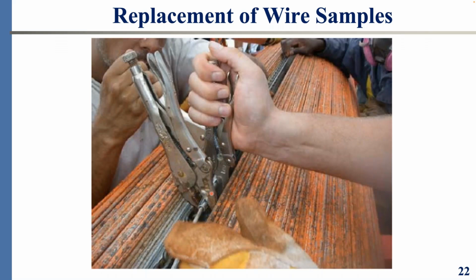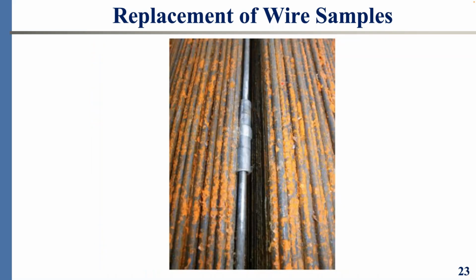And with a pair of pliers on opposite sides, because the turnbuckle is designed that way, you tighten the wire and you bring it back to service load, or use a load cell to measure the load in the wire. So it is surgical with very rudimentary appliances. And here is the turnbuckle sitting comfortably, and the new wire is back where we took the samples. So we don't do anything destructive. In fact, we are very careful when we do that. We do it with surgical precision. If we cannot reach a wire, then we don't sample it, period.